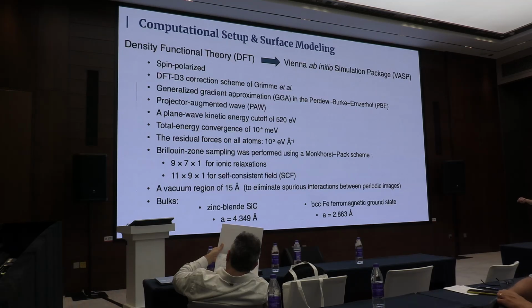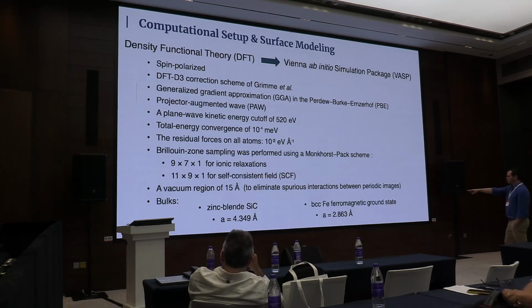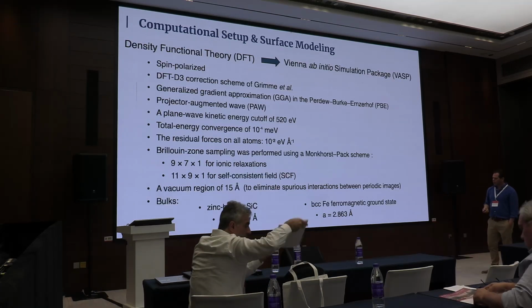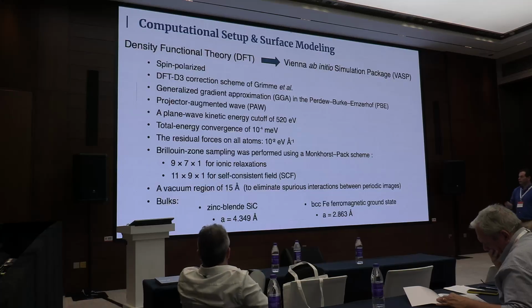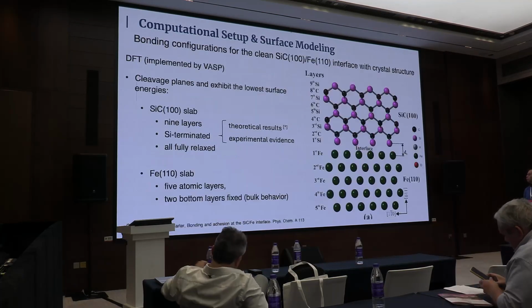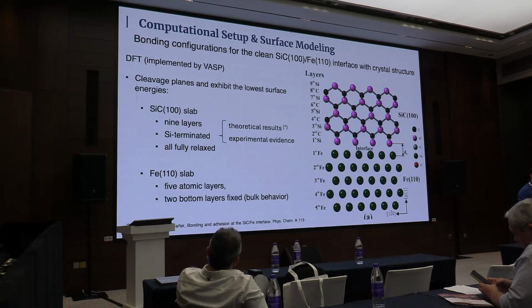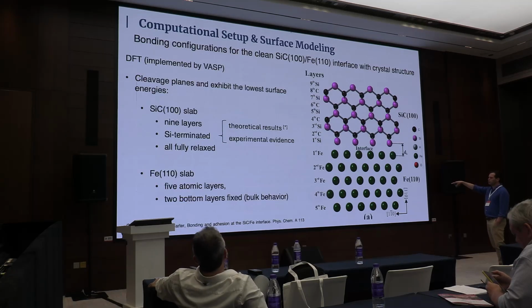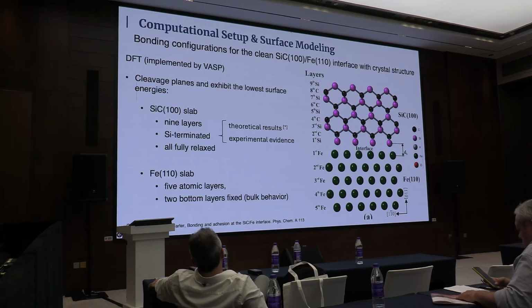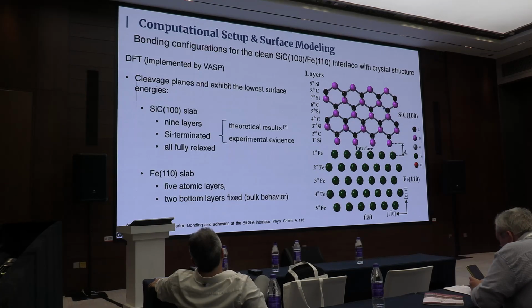So for that we first make a full computation in order to build iron, but it's going to be just pure iron, and then I will build a silicon carbide, just a pure crystal one. But the reality is that the experiment has an amorphous one. And here there is another addition of iron, but we have pure iron here. So the model will be like this. We will have first in the lower part the substrate and the interface here.